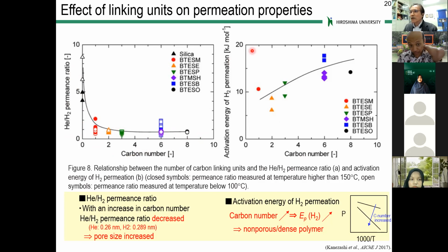Now, when you look at the right side figure, with the increase of carbon number, the activation energy of hydrogen increased. The activation energy is indicated as the slope of the Arrhenius plot. This suggests non-porous membranes. With the increase of carbon number, activation energy increases.